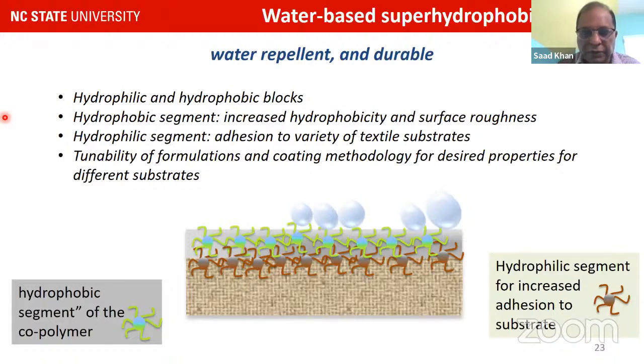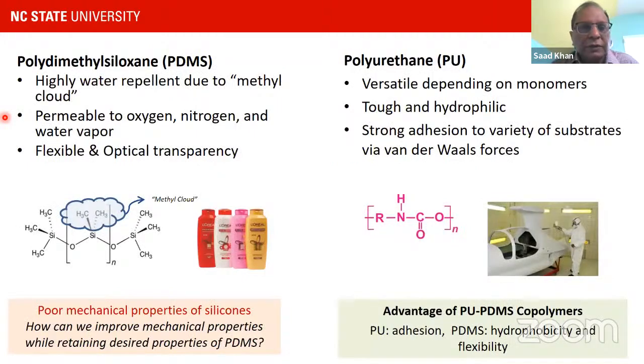So we did a very simple approach. We took PDMS, which would be the hydrophobic moiety. It is flexible and hydrophobic. The problem is that it lacks some of the mechanical properties that you want. And so the other moiety in the block copolymer would be polyurethane. It can have strong adhesion to various substrates, and we have seen that. It's tough and hydrophilic, and so we would like to combine them.